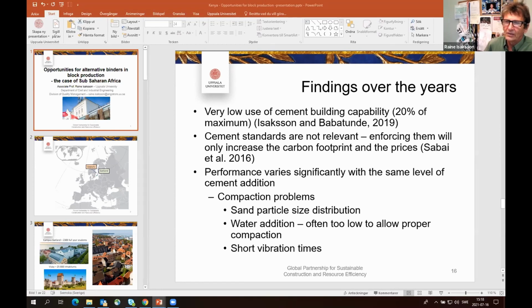Cement should go to high rises, to bridges, to whatever demands its good capabilities. It should not be wasted on simple blocks that need a couple of megapascals. Cement standards are not relevant. We looked at this in Tanzania. If we would increase the cement amount to what the standard requires in megapascals, the only effect is that the cement becomes more expensive, buildings become more expensive, the carbon footprint is higher, but the functional value for the customers is basically the same. So standards are partly a problem.